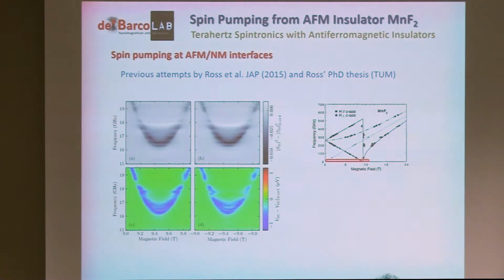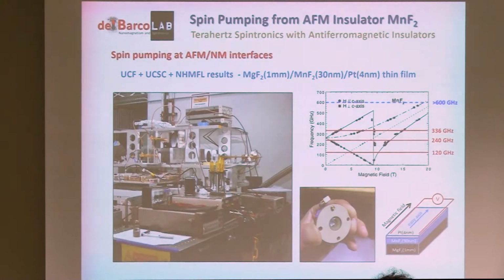All right. So the problem is that when they went to look at the voltage that they were expecting from the spin pumping in the platinum, they didn't observe anything. Well, actually, yes, they did. So this is the spectroscopy that I showed you before, and this is the voltage measuring platinum. They did observe a peak, but it didn't reverse with the polarity reversal of the magnetic field, as you would expect with spin pumping, right? And then they associated this to some kind of micro-rectification in their setup, and they were basically not able to complete this measurement.